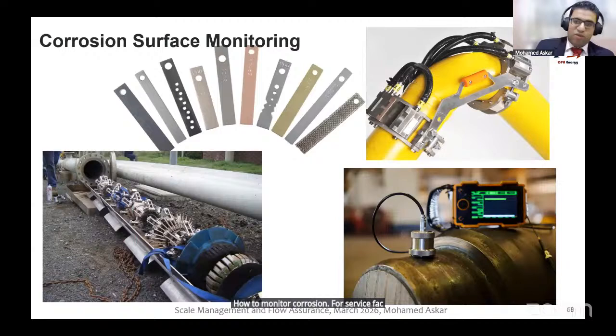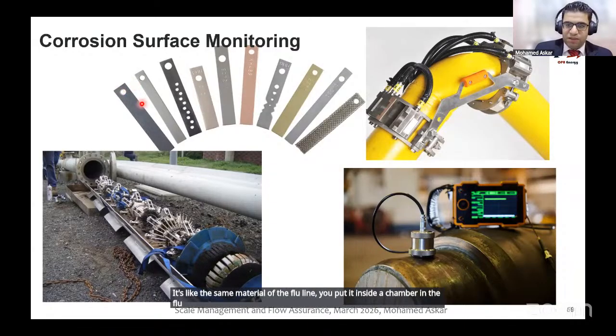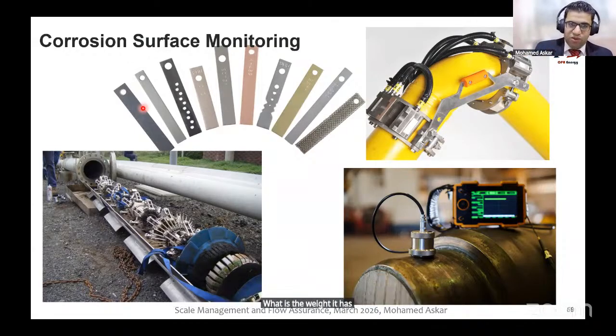How to monitor corrosion? For surface facilities, we use a corrosion coupon. This is the same material as the flow line. You put it inside a chamber in the flow line, and after some time you retrieve it to see what weight it has lost during production. It will lose weight due to corrosion, right? And these holes, if you remember, may be used for a scale coupon. If you have some plugging in these holes, it means you have some scale deposition, right?